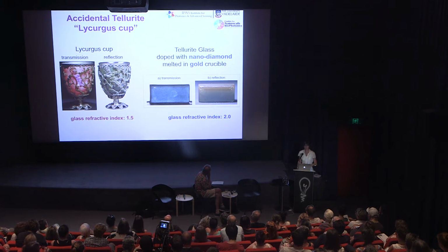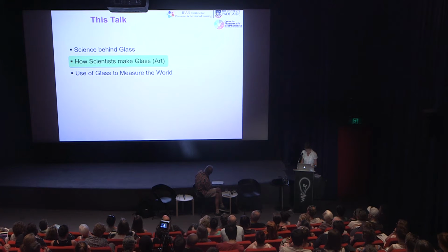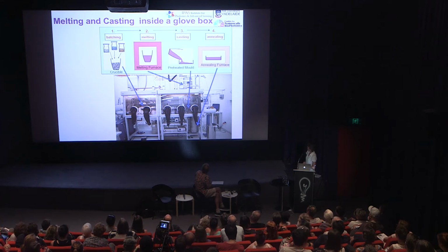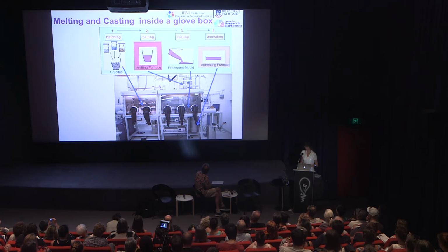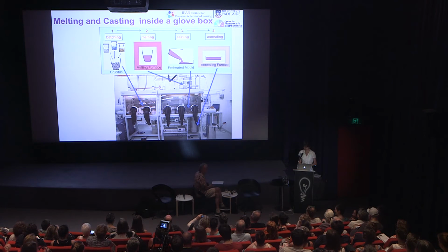And so then you have seen in the previous slide that we managed to make a colorless glass. What it really meant is to perfect the process so that we minimize the dissolution of gold from the crucible. So now a few slides on how we make our glasses. We also use furnaces, a melting furnace and an annealing furnace, but they are attached to a glove box so that again we can control the atmosphere in which the glasses are made. Apart from this, everything is the same: the batching, the melting, the casting and the annealing. But it's done under controlled atmosphere so that we can play with the redox conditions in the glass and also protect the glass from the moisture in the air.